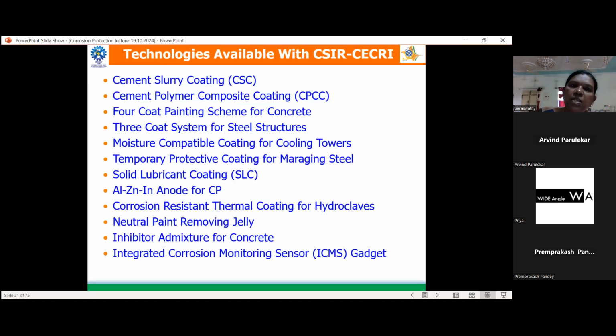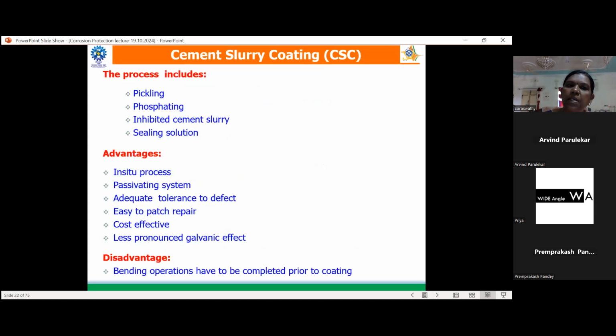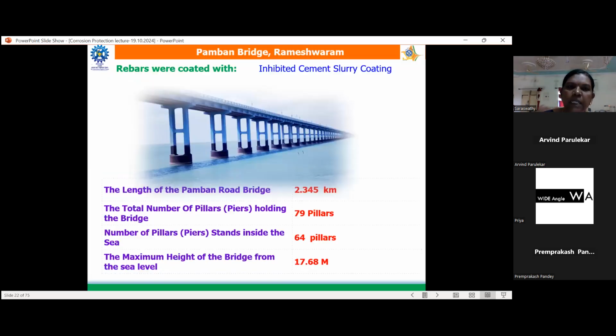So this first one is a cement slurry coating. This cement slurry coating consists of inhibitor plus cement. This is a 4-step process, and this technology has been used in the Pamban Bridge, which is located near Rameshwaram. This is the birthplace of our past president, ex-president Abdul Kalam ji.